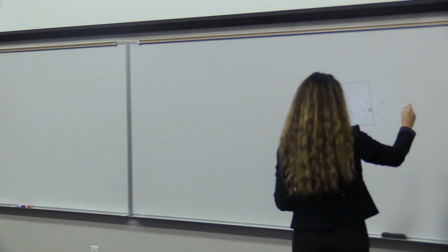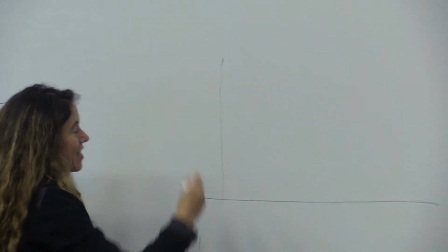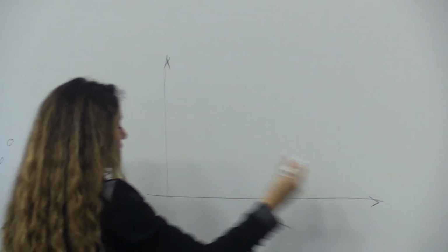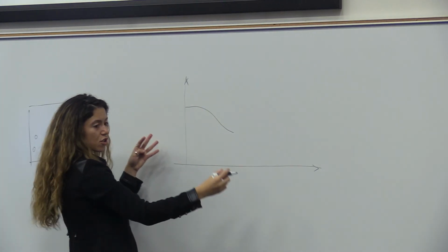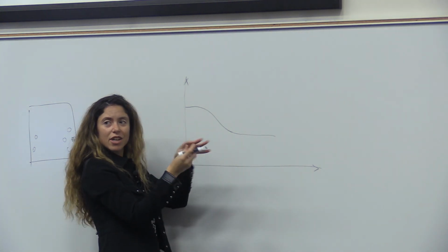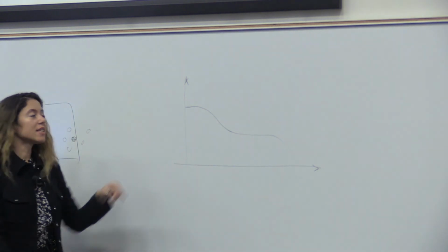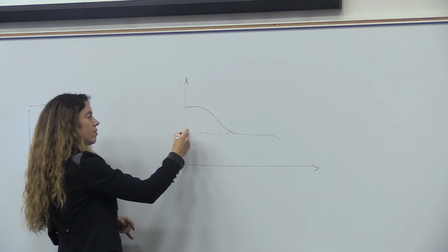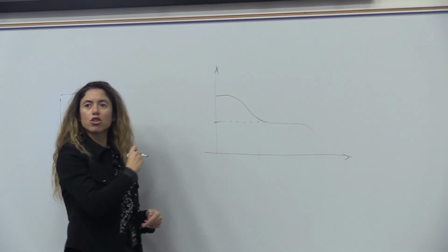Yes, so I think that you're referring to the Plateau Modulus. So when those systems are stressed and then relax, the stress somehow decays as you leave it, but it reaches a plateau because it is entangled. It needs some time to find its way until it drops. And this quantity where it stops for a while is called the Plateau Modulus.